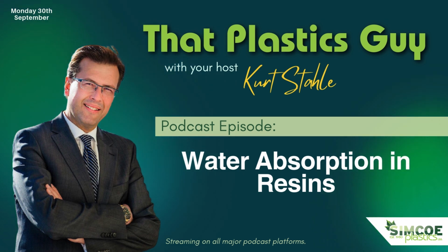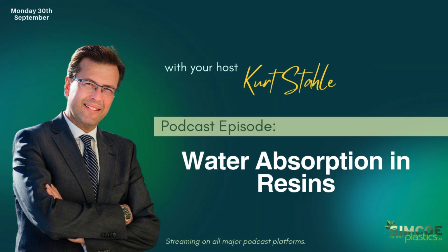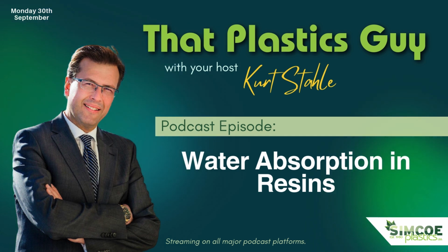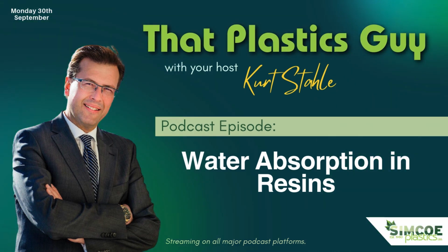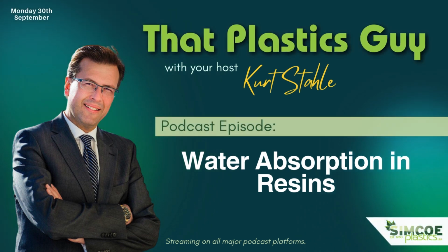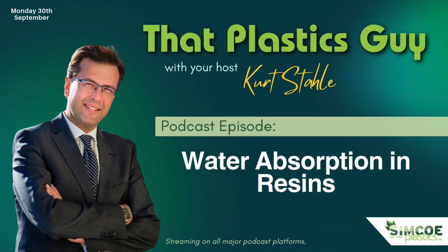Now I'm going to go past some of the styrenics. I want to get to a few other things that we may encounter on a regular basis. Okay, so here's another one. This is a material that really is not absorbing moisture tremendously, but I'm just going to give you this data to make the point. EVA, ethylene vinyl acetate: its dry state 0.005 of a percent of moisture, max moisture 0.13. So it's not a significant increase in moisture. Well, maybe in terms of a percentage change it's still significant, but overall, 0.13 of a percent max weight.